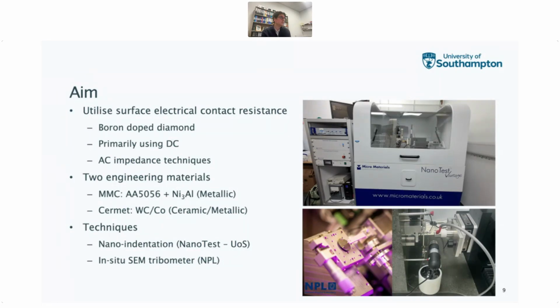And then the techniques we used, you can see the Micro Materials NanoTest system that we have here at Southampton was our primary platform, and I'll just explain how that works zoomed in there. But we also collaborated with our project partners at the National Physical Laboratory. And they have this in situ tribometer that you can insert into your scanning electron microscope, which is quite useful for the vacuum techniques, which I'll explain a little bit later. But you can see it has this inclined surface stage such that you can allow the electron beam to penetrate the area of interest and observe what you're doing there.